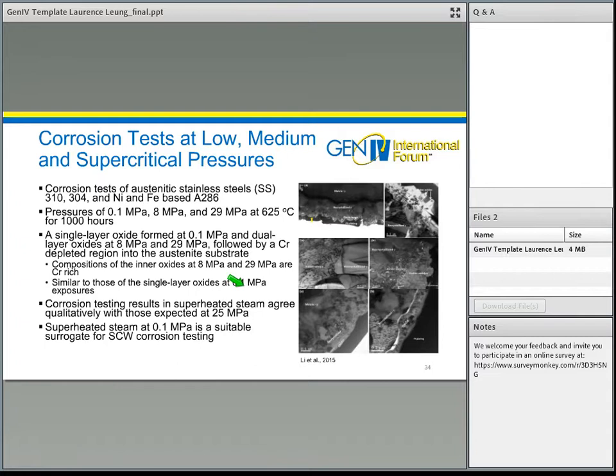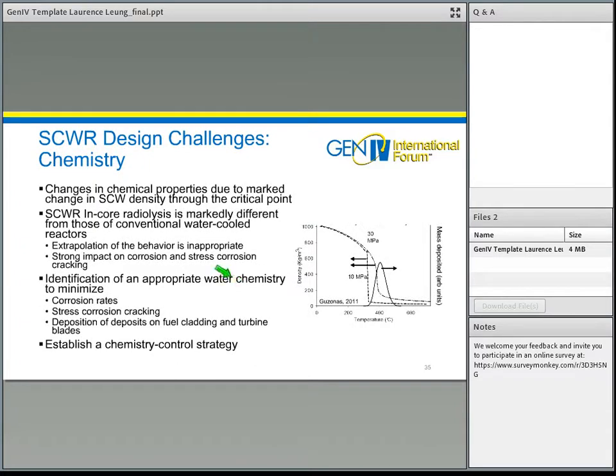From the chemistry standpoint, the change in chemical properties is very drastic and expected at the supercritical point. The radiolysis characteristic in the SCWR in-core is quite different from the current water-cooled reactors. This figure shows the density variation with temperature. At low pressure, the density has a sharp drop at the saturation point. In that case, the majority of the reactor operates in the high density region, except for accident conditions where you drop to the low density region.